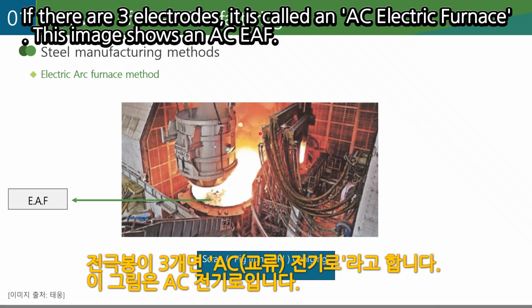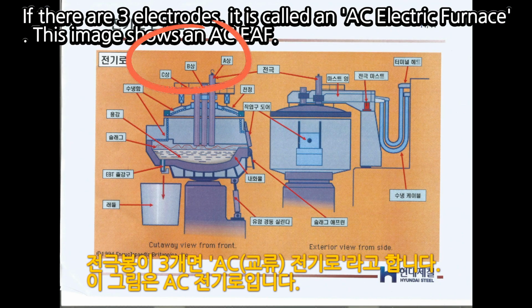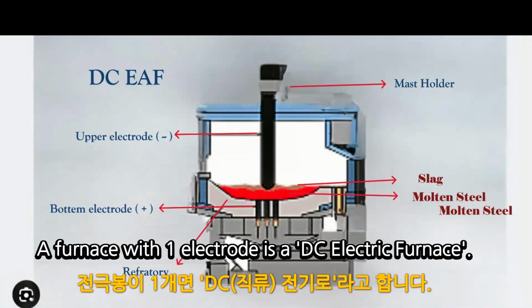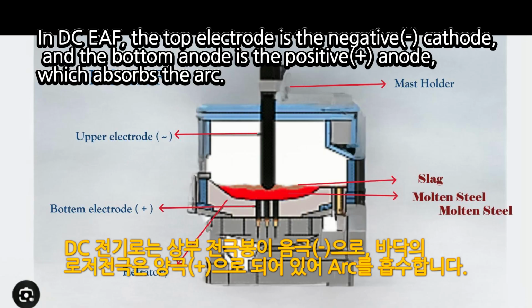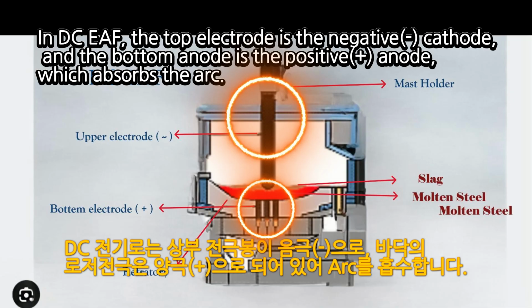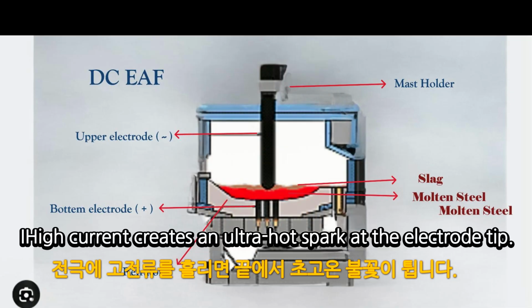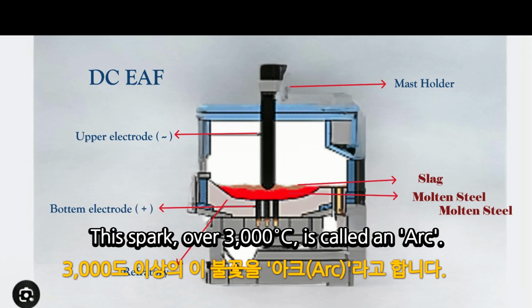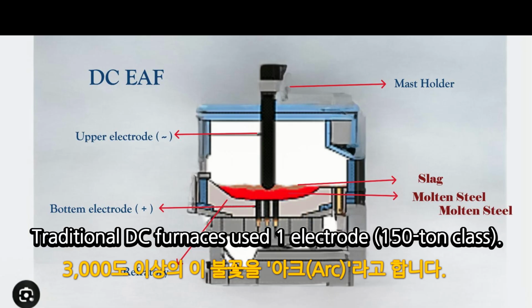If there are 3 electrodes, it is called an AC electric furnace. This image shows an AC EAF. A furnace with 1 electrode is a DC electric furnace. In DC EAF, the top electrode is the negative, the cathode, and the bottom is the positive, the anode, which absorbs the arc. High current creates an ultra-hot spark at the electrode tip. This spark, over 3000 degrees Celsius, is called an arc.